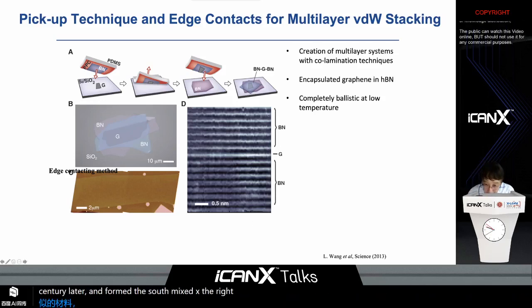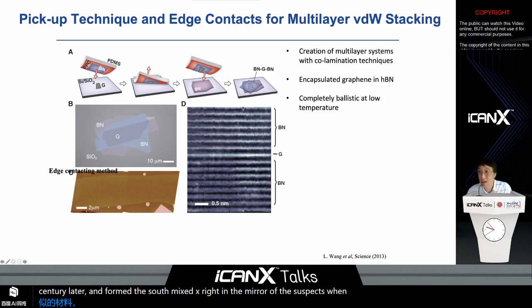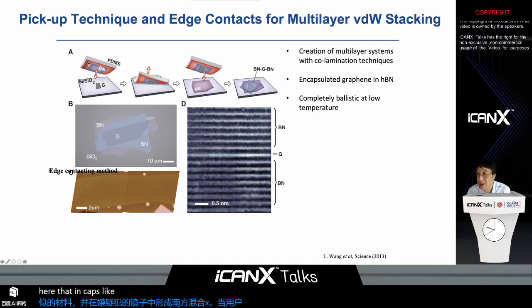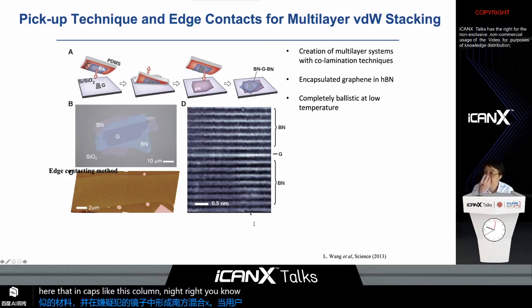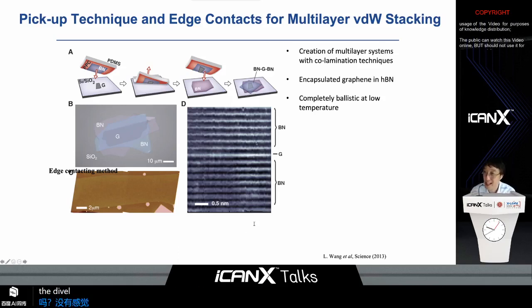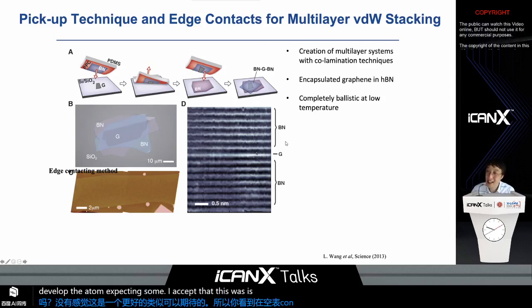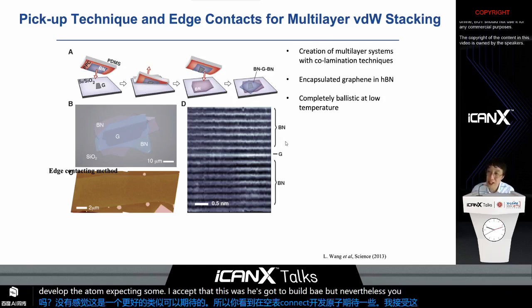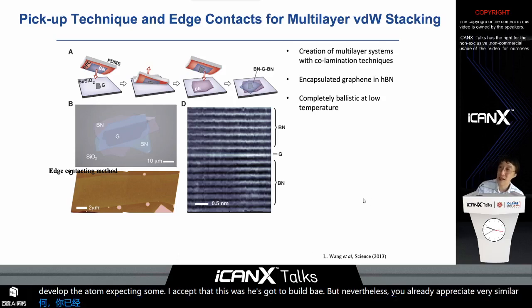In the middle of this stack, when you just cut it out, you show this TEM image. The graphene layer is here, encapsulated by this boron nitride. In a sense, this is a very similar atomic stack to what you saw in the MBE type of techniques that developed the atomic stack in semiconductors, except that this was basically built by hand. But nevertheless, you already appreciate the very similar flavor, that we can make this atomic stack with very simple techniques.